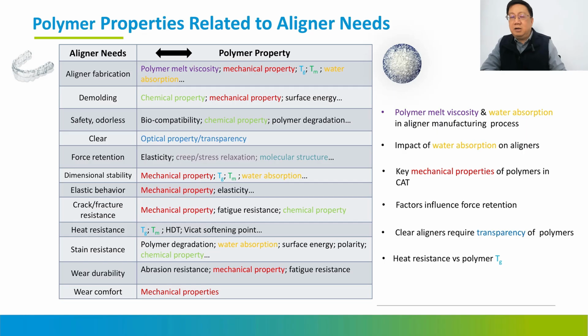the Invisalign material, whose surface is very soft. They have a problem with sticking to the dental model. So you need some kind of release agent, or you need a protective film. This protective film may be made of polyurethane material, which has lower surface energy, to help make the demolding process easier. So the third step, we're talking about safety and being odorless.